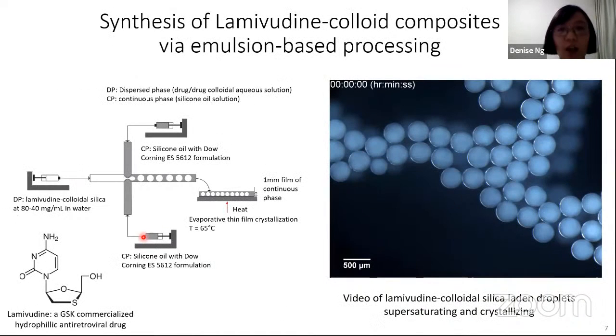So we start off with a hydrophilic drug. Our model hydrophilic drug for this demonstration is lamivudine, which is a GSK commercialized hydrophilic antiretroviral drug. In a typical experiment, we dissolve lamivudine at a concentration of 80 mg per ml in water, and we disperse the colloidal silica into the same dispersed phase. It is then emulsified into monodispersed droplets using a continuous immiscible silicone oil phase. And these monodispersed droplets are collected into a thin film of 1 mm of the continuous phase,